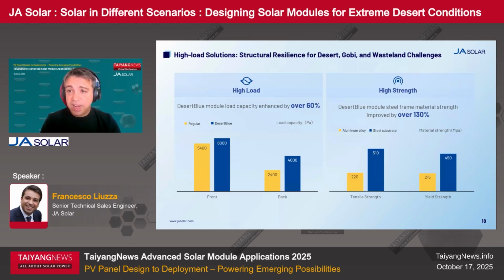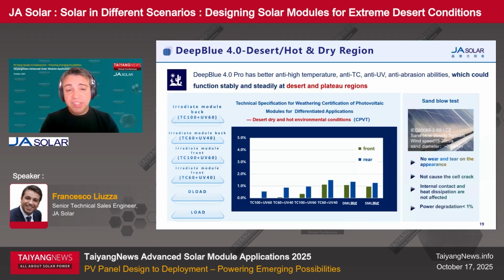And in terms of strength of the steel frame, in terms of tensile strength and yield strength, you can see how the steel substrate with the specific design can increase the overall strength of the modules. Modules of these years were tested in laboratories with a specific sequence dedicated for desert dry and hot environment conditions, through different cycles of thermal cycle and UV doses, coupled with the dynamical and mechanical load test, and also sand blow test, which shows that in very severe conditions, no cell cracks, internal contact and deformation are not affected, and there are very low losses and degradation.